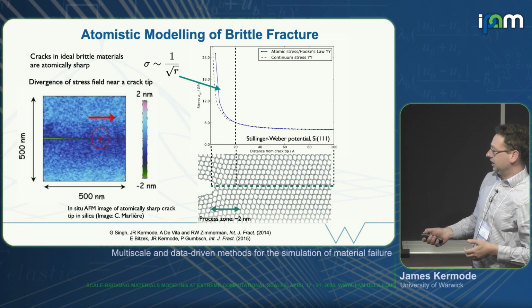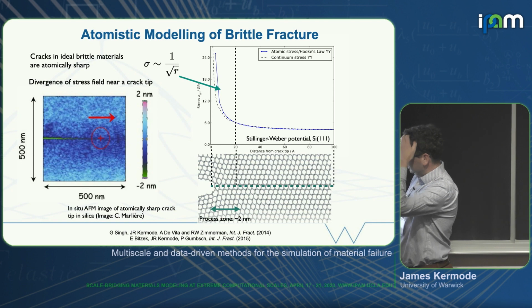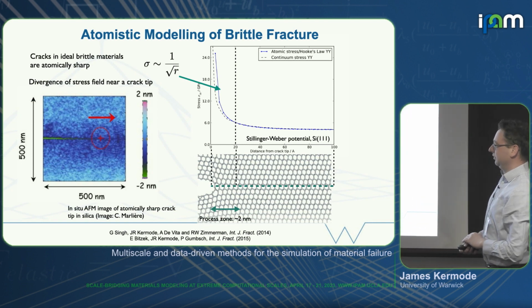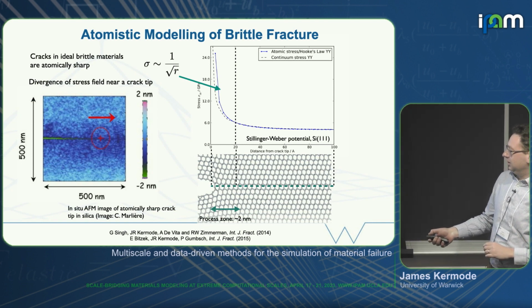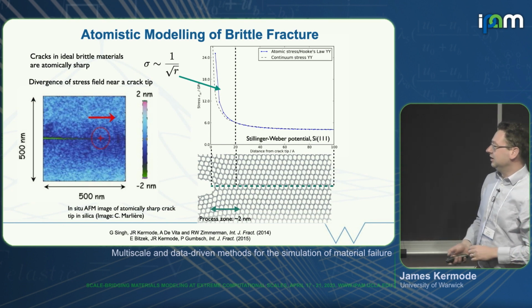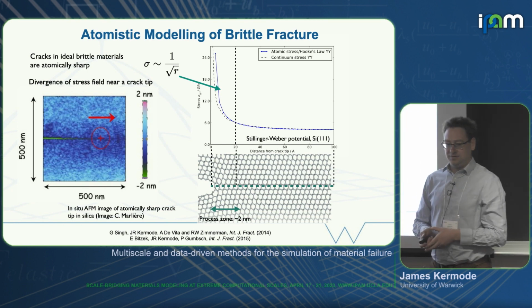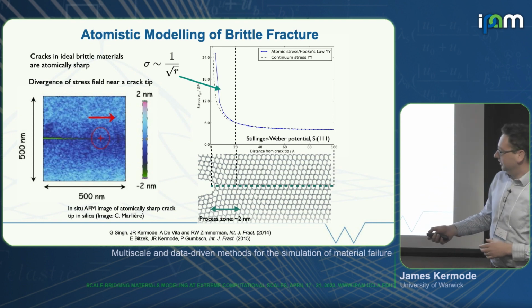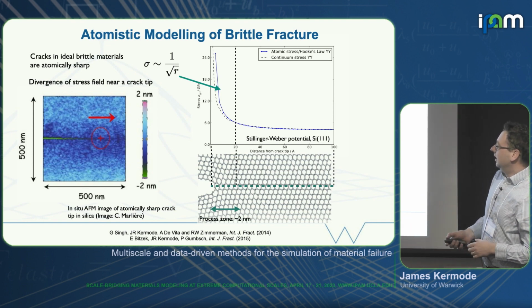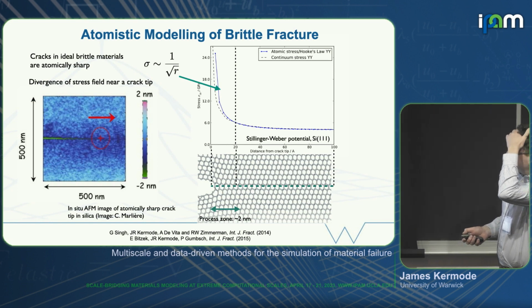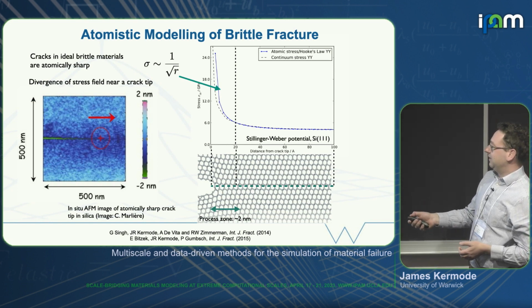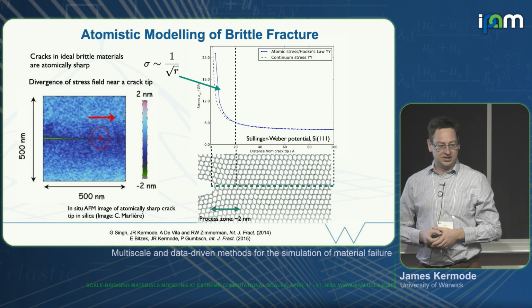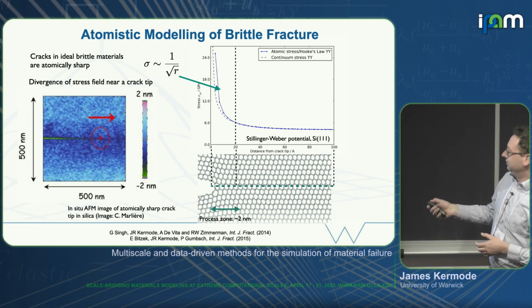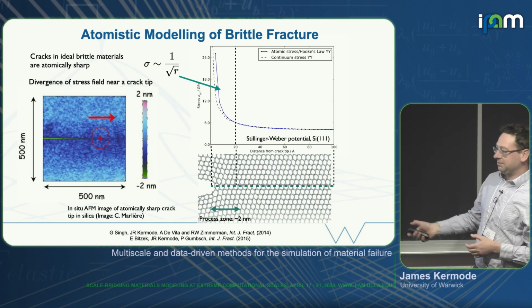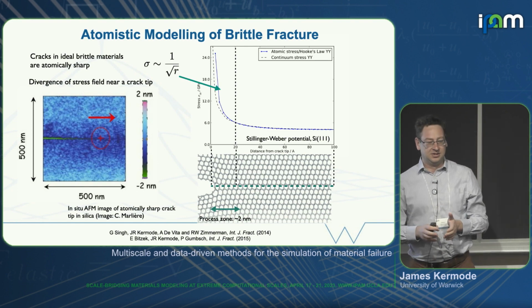This is a brittle material, this is glass. Actually, here we have silicon, this is silica, but similar material responses would be expected. If we look in an experimental image, an AFM image, we see that the crack should be mirror smooth and atomically sharp right down to the very tip. And this is on the nanoscale. If we look at the comparison between a continuum model, where we expect stress to diverge as 1 over square root r as we approach a tip, and an atomistic calculation, we see perfect agreement beyond a couple of nanometers ahead of the crack tip. So the process zone in a perfectly brittle material really is nanoscale.